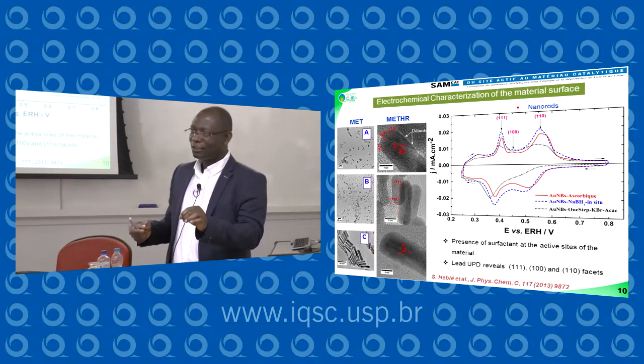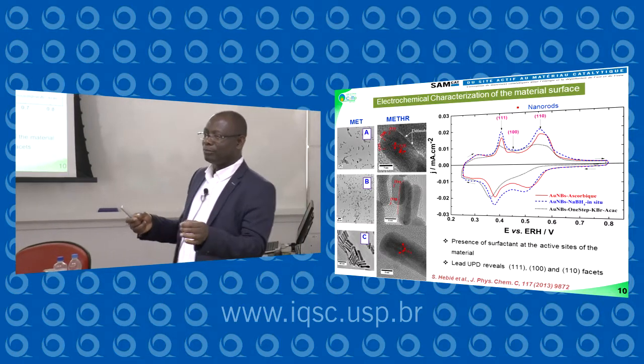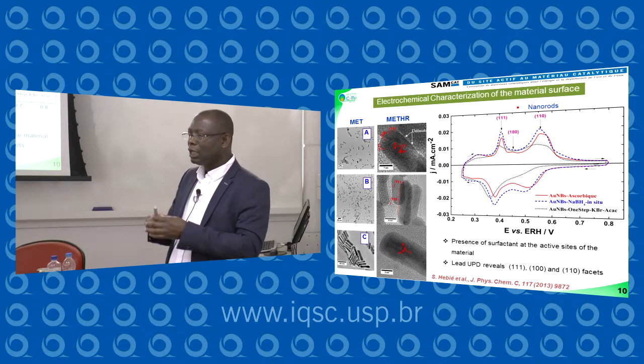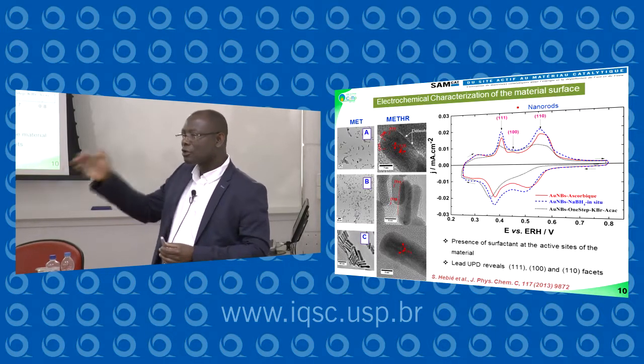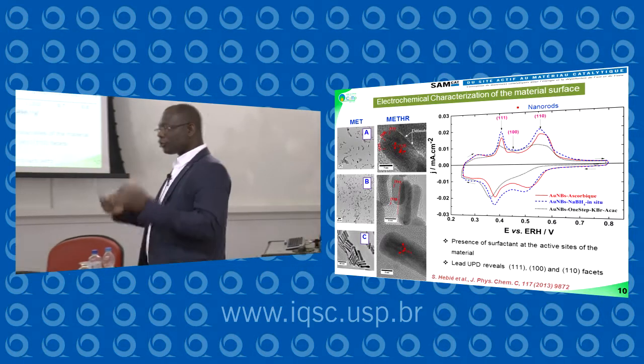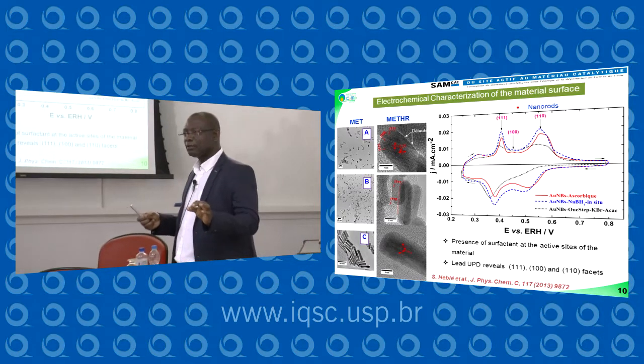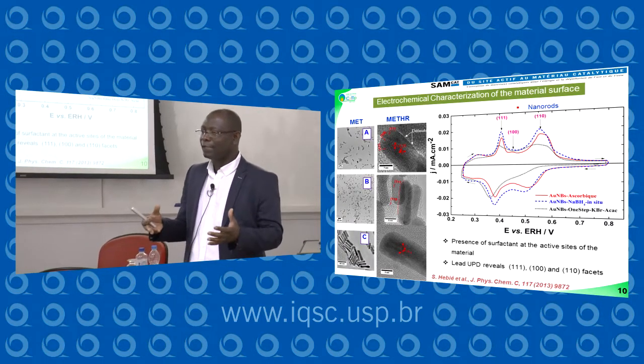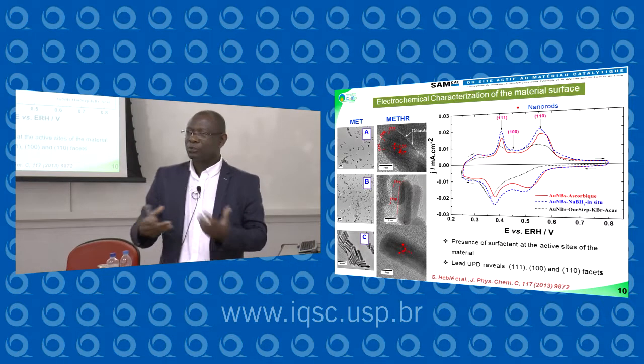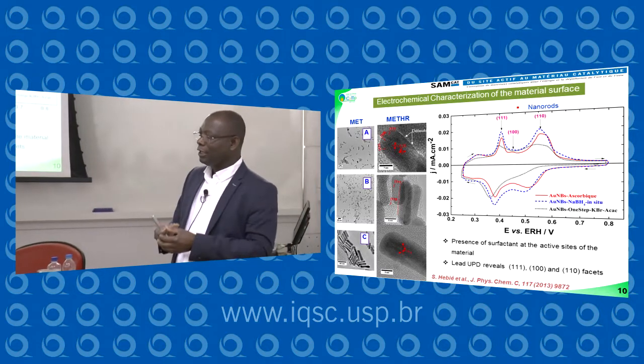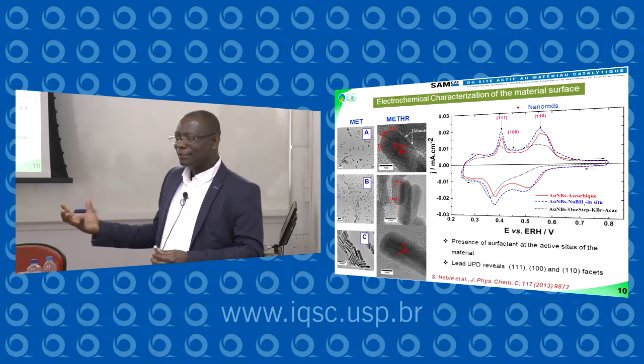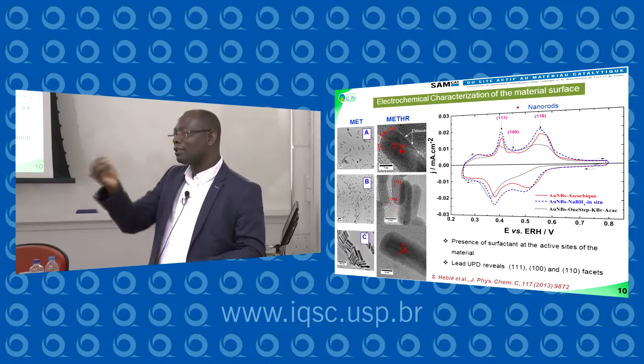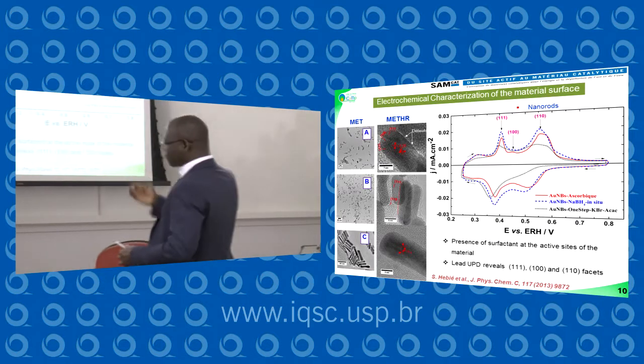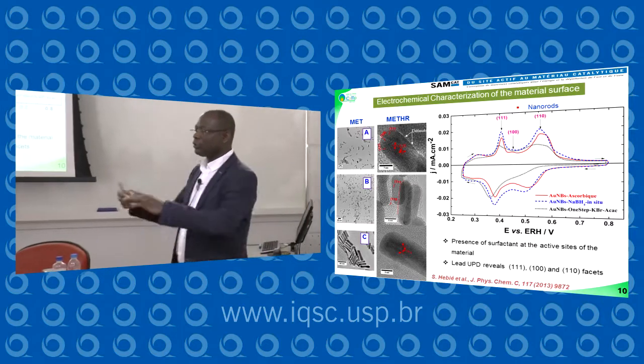But when you start electrochemistry characterization, you have a problem, because you have to cycle 20 times to remove the surfactant at the surface of your active site. This means that if you can prepare something without a surfactant, it's beneficial for electrochemistry. But the problem is when you discuss with physicists, they say that chemists have a good method to prepare nanocatalysts, but the problem is the organic compound. So we have a new method to remove the surfactant. We call it a surfactant-less method, and we improve the catalyst surface area.